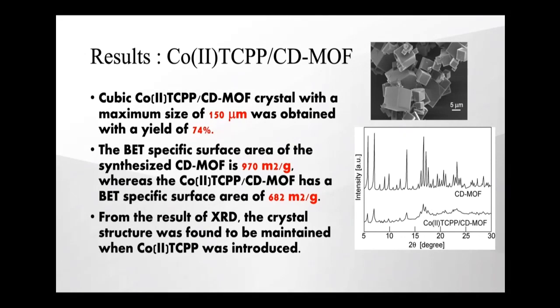This part is the result of crystallization of CDMOF. As shown in this SEM image, cubic cobalt TCPP CDMOF crystal was obtained. The crystal size was 5 to 20 micrometers. When the crystallization conditions were changed, the crystal grew up to 150 micrometers. From the result of XRD, the crystal structure was found to be maintained when cobalt TCPP was introduced. The BET specific surface area of the synthesized CDMOF is 970 square meters per gram, whereas the cobalt TCPP CDMOF has a BET specific surface area of 682 square meters per gram.